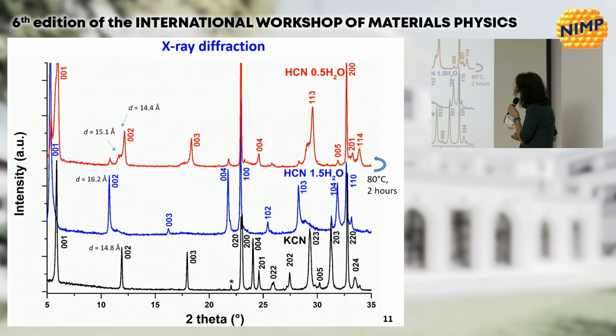Also, we can check the process by X-ray diffraction, and in particular, the parent compound has a strong peak related to the basal plane, and this peak is shifted because the interlayer spacing has changed. So this is a way for us to control that the process is running well.